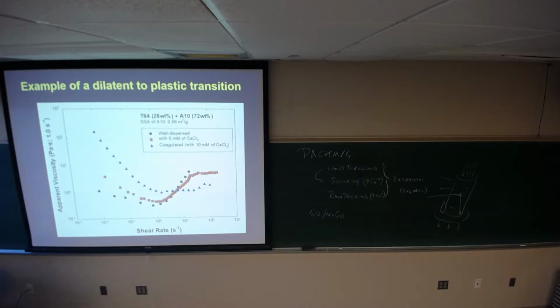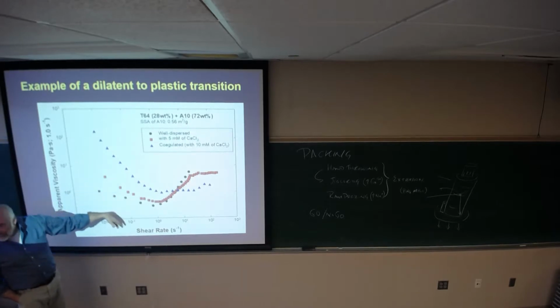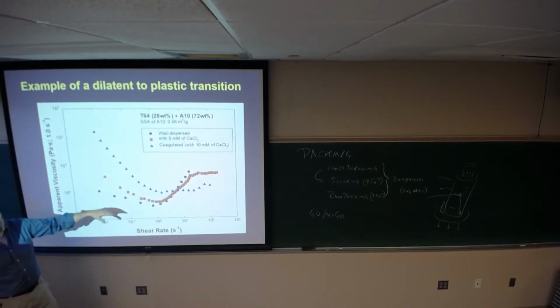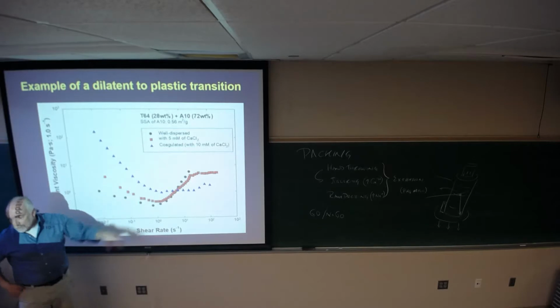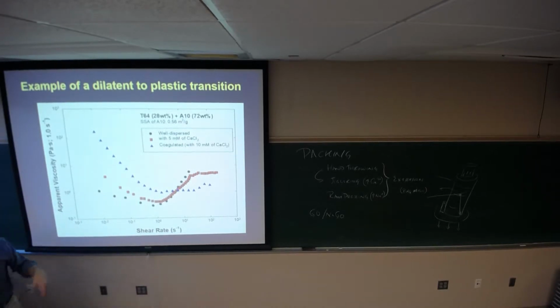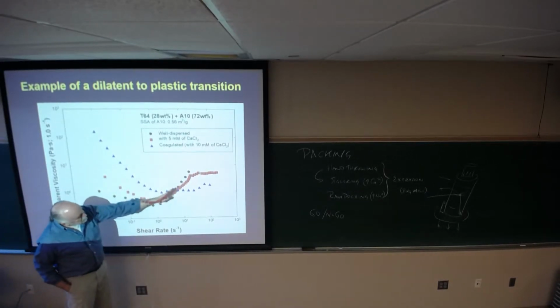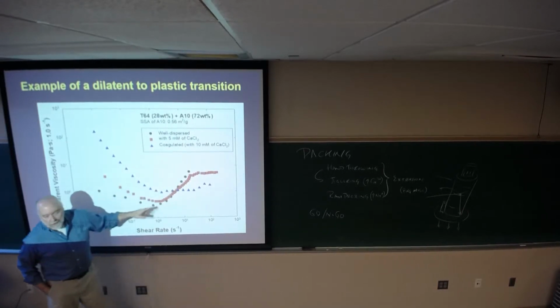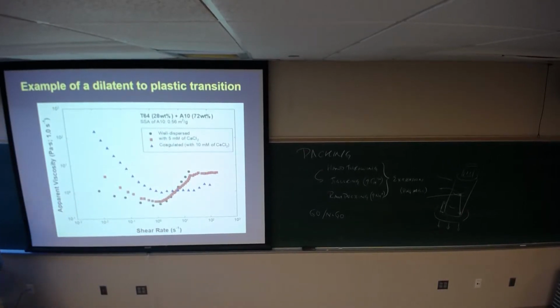So if I set up the jigger and I have a certain speed, okay, ideally that speed is shearing within this range, okay, and then everything's forming. And if I go too fast, I start tearing them apart. So I generate defects. So what this shows me, and this is an alumina, right? No intrinsic plasticity to speak of. Although we're able to get intrinsic plasticity in that material by increasing salt concentration, that I can change from this to the plateau, I can change the way that material behaves in the forming process by controlling particle interactions.